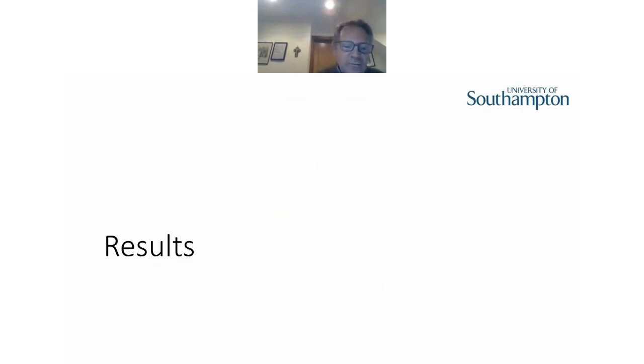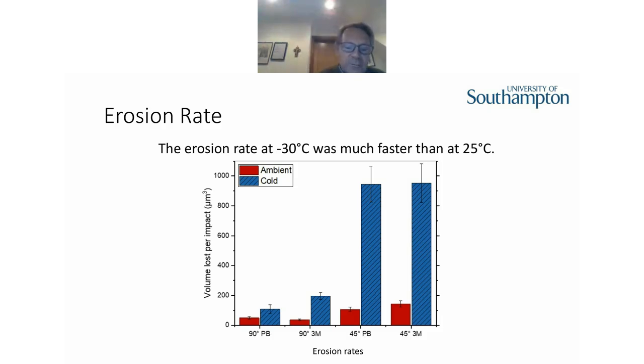So just quickly, some results. The red on the left-hand bar charts here is for ambient, and the blue are the colder ones. So there is an influence of angle, and there's certainly a very big influence of temperature. As you go down to minus 30, the erosion rate dramatically increases, and then obviously there's a subtlety between normal impact and 45. Those were the basic results, and we plotted them here.